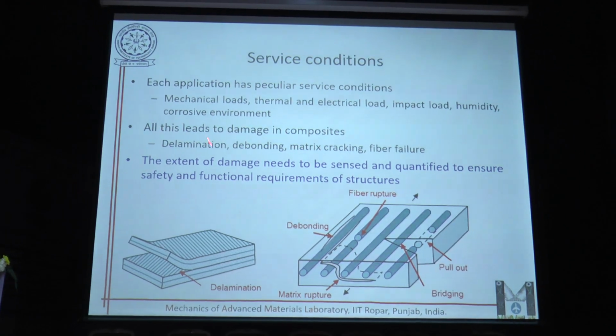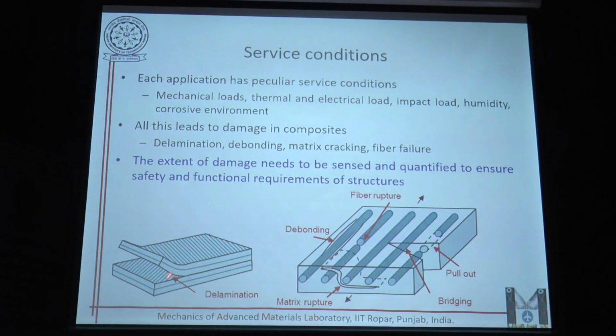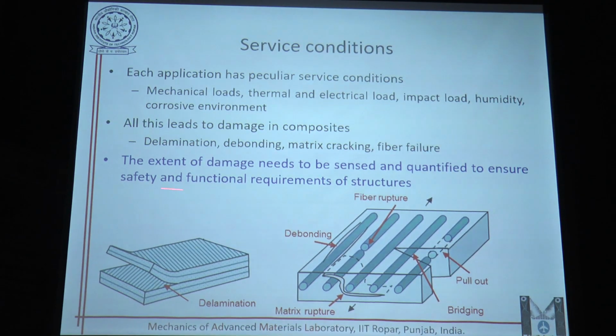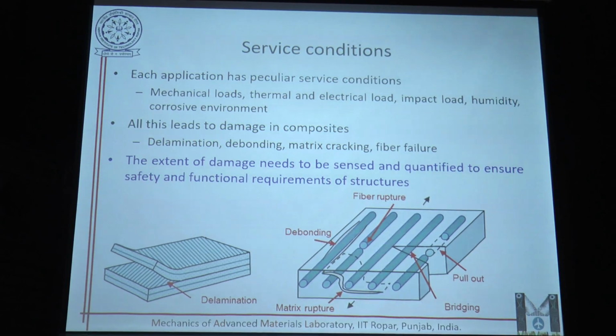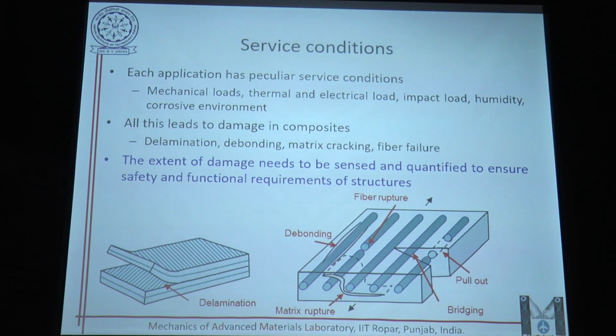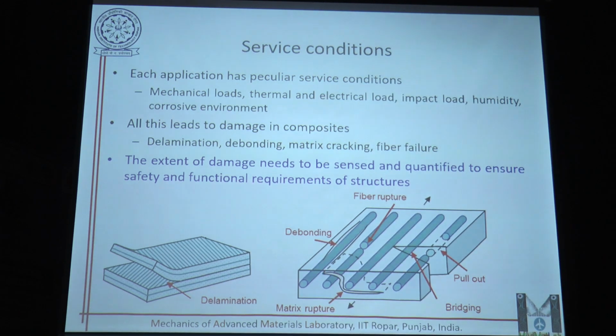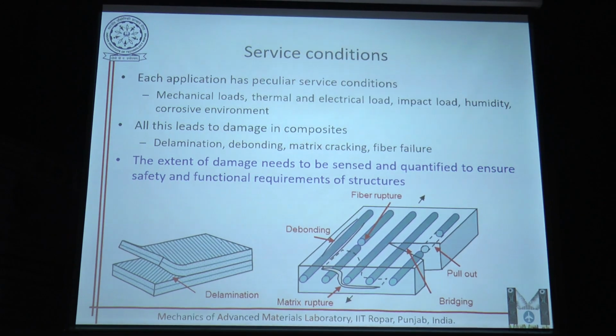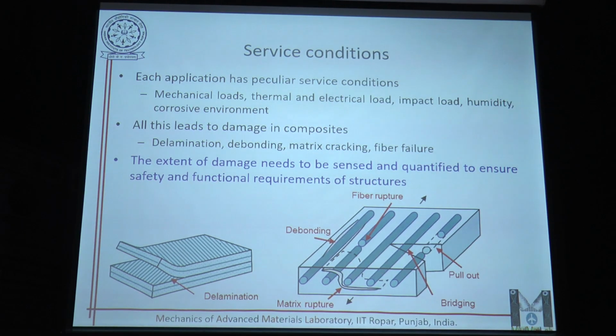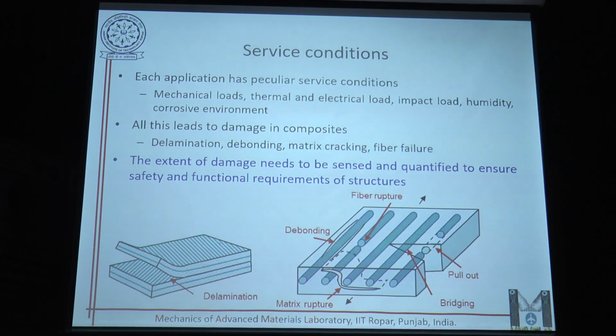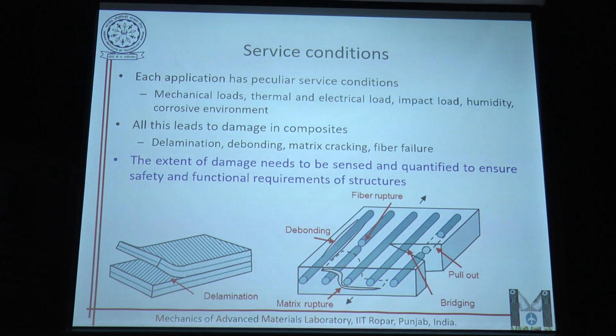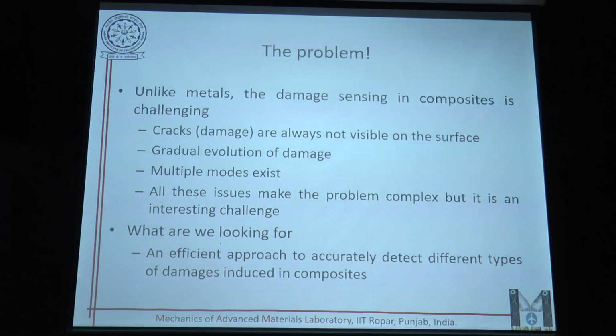One of the primary damages in composites that we all know is delamination, which is the breaking between the plies, or debonding, which is the failure of the bond between the matrix and the fiber, matrix cracking and fiber failure. Now, when we want to ensure the safety of operations during service conditions, it is very important that we are able to quantify and assess this damage. Where is the damage, how wide is the damage, and how is it going to affect the service life of the component? These are very important questions that we need to ask, and we are trying to address them through the intervention of nanotechnology in the composite design itself.